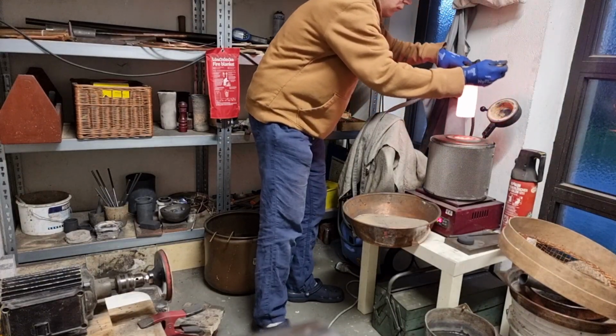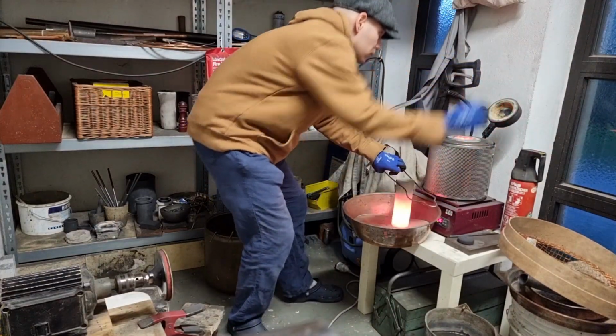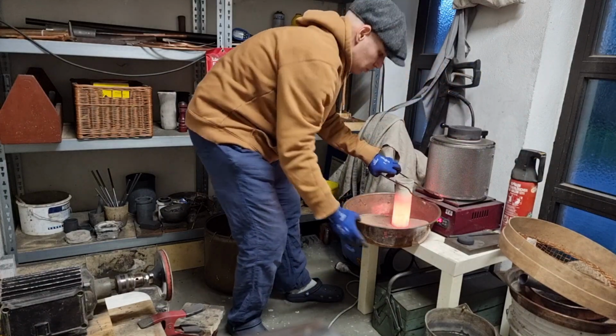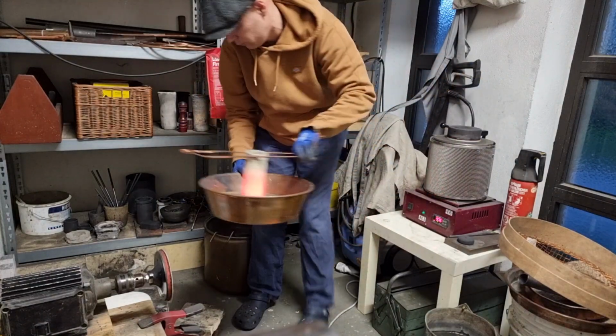Yes, I forgot to mention that this first heat treatment, the 6 hours, was at 900 centigrades. So 6 hours at 900 centigrades in order to decarburize the surface of the white cast iron.